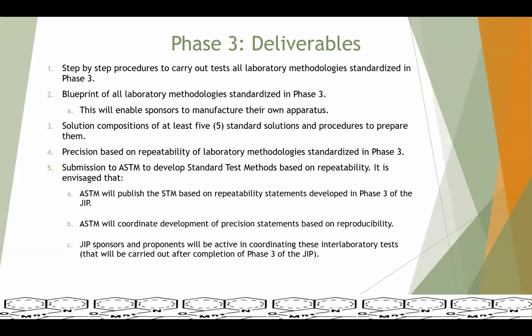When we did the interviews, it became very clear that if we want to standardize a laboratory methodology, we need to also standardize the standard solutions. When we say solutions, it also includes saturation of the solution with gases. If we do not have a set procedure, then that can lead to variations in the test result. So one of the side benefits or side outcomes of this JIP would be to establish a standard on solution preparations.